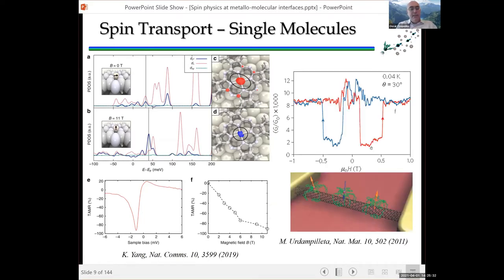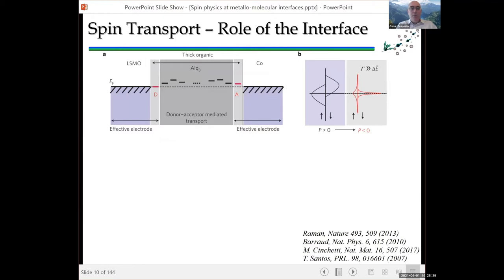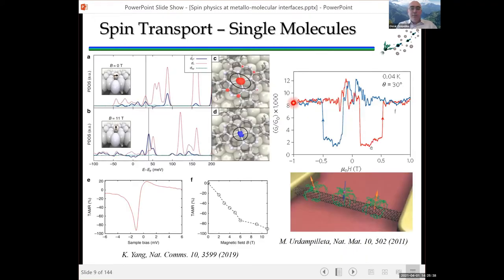Another very interesting study in magnetoresistance in single molecules, for me, was the paper from the group of Wernsdorfer, where they actually managed to fabricate a spin valve just out of single molecules. So they had 3 molecules with a superparamagnetic spin center in the carbon nanotube, and they cool it down so that the superparamagnetic centers would be stable in the magnetization direction over the measuring time of the experiment. And depending on the relative alignment of the spins of the 3 molecules, they could see the magnetoresistive effect typical of magnetic tunnel junctions or spin valves, but at the single molecule scale.